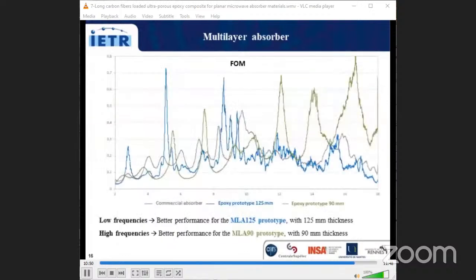From these 3 FOM curves, we can say that at low frequencies we obtain better performance for the epoxy prototype with 125 millimeters, here the blue curve, and at high frequencies the better performance is obtained with the epoxy prototype of 90 millimeter thicknesses, here in a green curve.